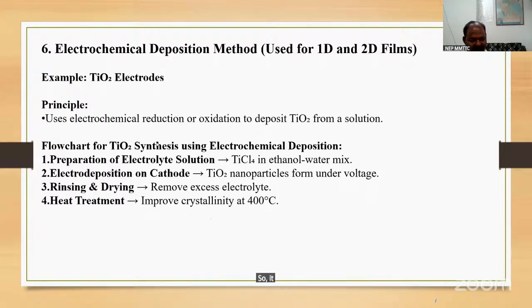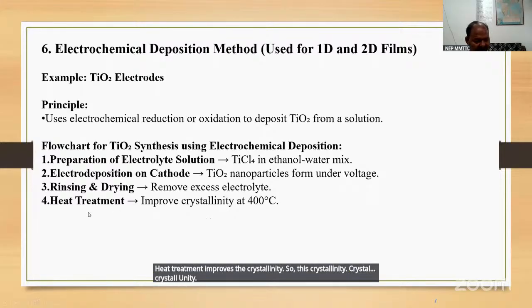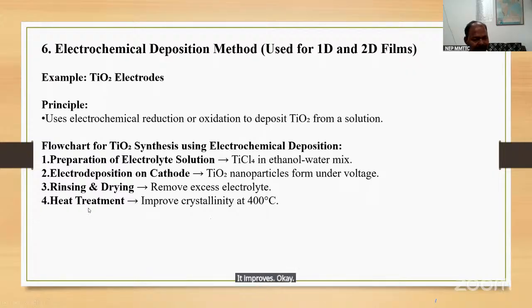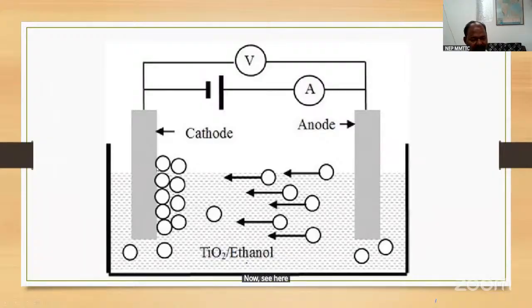under the voltage. Now rinsing and drying to remove excess electrolyte, then heat treatment at 400 degrees Celsius. Heat treatment improves the crystallinity. Okay. Now see here the deposition. This is the anode and this is the cathode. This is the TiO2 and this is the solution of TiO2 and ethanol. Voltage, okay.